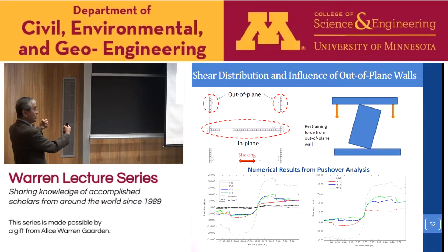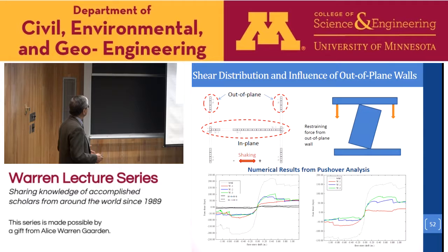So we did two pushover analyses to demonstrate that, one with the out-of-plane wall, the other without the out-of-plane wall. You can see that the difference is quite significant. If you look at just the bending resistance of the in-plane wall, it is only 5% of the total capacity. So this really concludes.